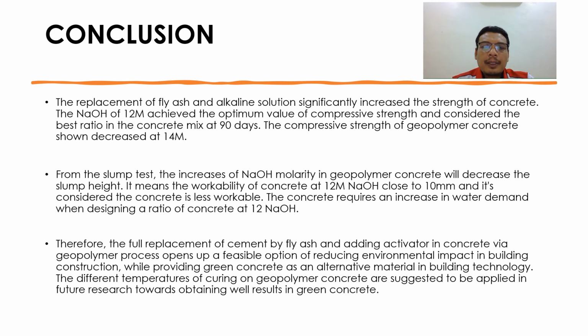Next, from the slump test result, the increase of sodium hydroxide molarity in geopolymer concrete will decrease the slump height. It means the workability of concrete at 12 molarity sodium hydroxide is close to 10 mm, and it's considered the concrete is less workable. The concrete requires an increase in water demand when designing a ratio of concrete at 12 sodium hydroxide molarity.